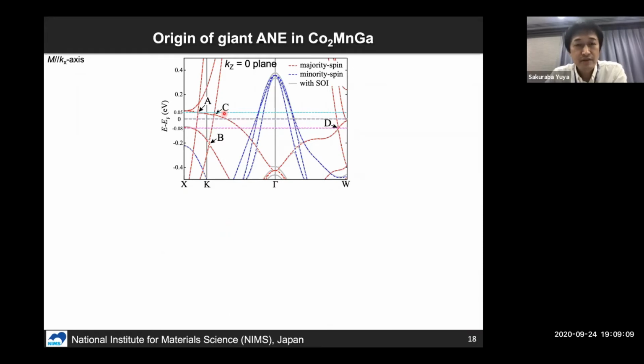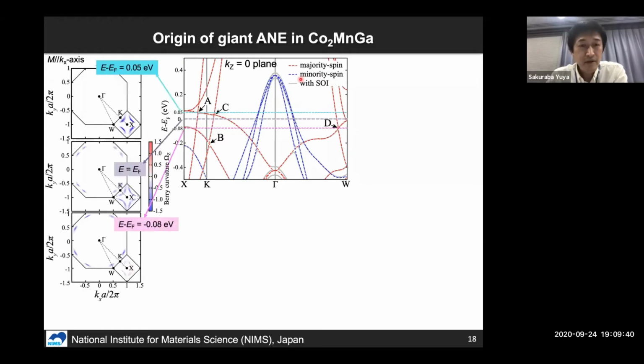So here I show the electronic band dispersion on the kz equal 0 plane and kz equal pi plane. In the kz equal 0 plane, the red and the blue dotted lines correspond to the energy bands of majority and minority spin electrons. And we also calculated the Berry curvature in this kz equal 0 plane.